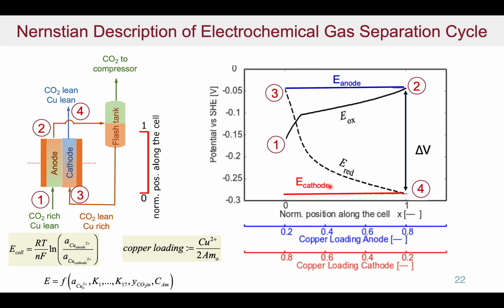I do want to point out one of the things that one needs to be concerned about. Those are thermodynamic equilibrium conditions. But we need to think about what the actual overpotentials are to drive that reaction at a reasonable rate. So if we now look at the system, we're interested in what the variation in potential is as a function of the position along the cell. So our copper loading goes from 0.2 to 0.8 here, and on the cathode side from 0.8 to 0.2. So you can see we've got the two curves as shown here for the reduction and the oxidation states.